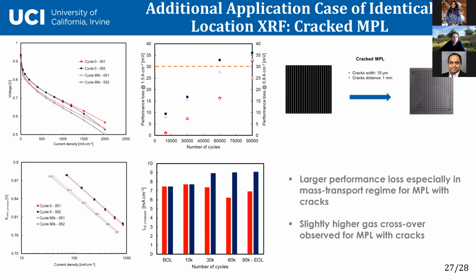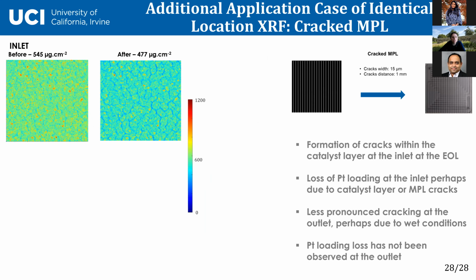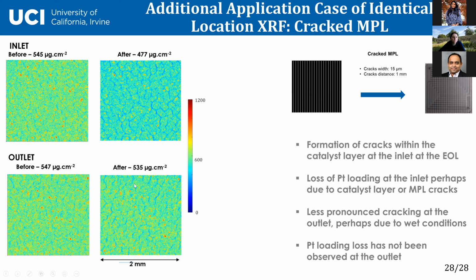But what's interesting was to look at the catalyst layer micro XRF, showing that microporous layer cracks actually do result in platinum loss. And that's interesting. So that confirms our early hypothesis that somehow water probably carries out platinum ions. And you see a lot of cracks forming at the inlet, less so at the outlet. And most of the loss of platinum is in the inlet.